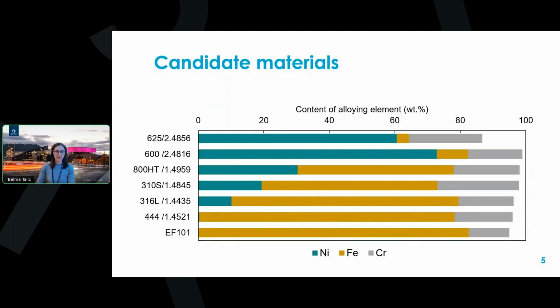For the experimental test campaign that we have done in the project, we have included 7 different alloys that you see listed here. These include nickel-based alloys in Inconel types. We have some austenitic stainless steels, a ferritic stainless steel, and an alumina-forming ferritic steel.